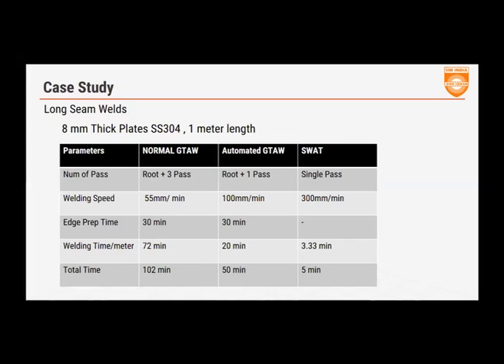If you were looking at long seams, and we welded about a 1 meter plate, 8 mm thick, SS304. If you were to do a manual GTAW process, the operator would do the edge preparation first on both sides, make the V grooves, get the two plates together, tack weld them, then do the root weld, followed by the hot pass, and then 2 layers of capping pass, fill up and capping.